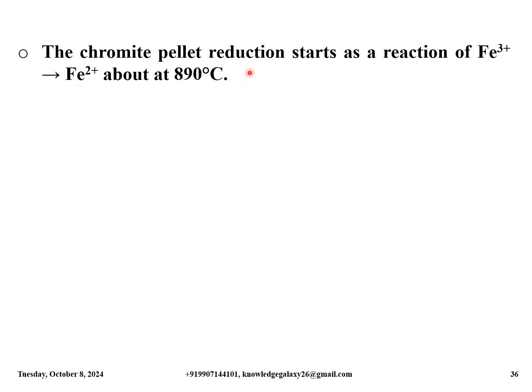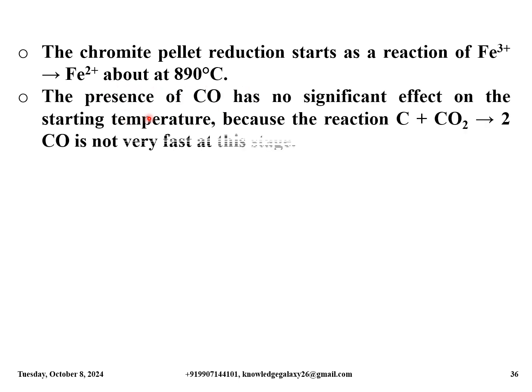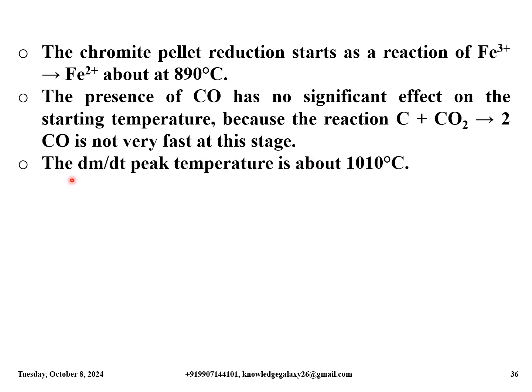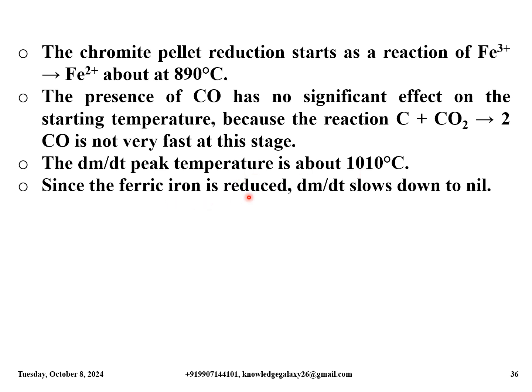The chromite pellet reduction starts as a reaction of Fe3+ leading to Fe2+ at about 890 degrees Celsius. The presence of carbon monoxide has no significant effect on the starting temperature because the reaction C plus CO2 giving 2CO is not very fast at this stage. The dm/dt peak temperature is about 1010 degrees Celsius. Since the ferric iron is reduced, dm/dt slows down to nil.